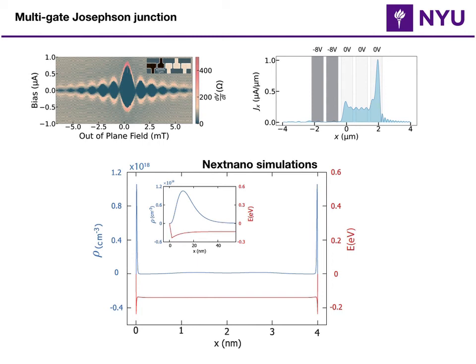So let me get back to these edge modes. Here is another example of a Fraunhofer pattern where the current is flowing through the right 3 mini gates. And if we do an inverse Fourier transform, you can see that the current reconstruction is showing a peak on the right and a more uniform current distribution in the middle. This is indium arsenide material, and we know that indium arsenide has a band bending effect near the surface. So we did the nextnano simulations, and indeed, very near the surface, the Fermi level goes above the conduction band, and you get extra carriers near that surface. Once that's happening, it allows more current to go through there. And maybe that's indeed the case here.